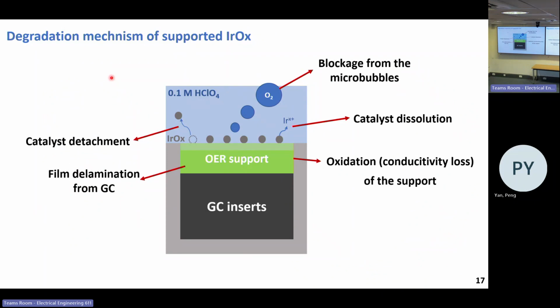So let's take a step back to look at the degradation mechanism of supported iridium oxide. First, we can physically lose iridium by catalyst detachment, and we can chemically lose iridium by iridium dissolution. Since oxygen evolution is a gas evolving reaction, bubbles can also block the active sites of iridium and cause degradation in performance. The degradation can also be from the support, like the support. The oxidation of the support can cause conductivity loss, and the support can delaminate from its substrate.